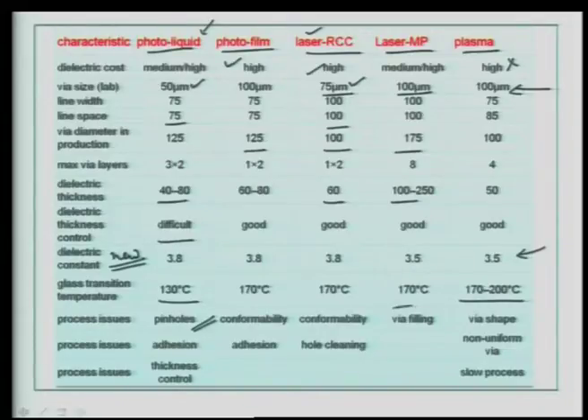In some cases, you may want to use a via filling, as I said, because you want to mount an SMD component on top of the via. Therefore, what type of filling you will do for the microvia filling, and the shape of the via in the case of a plasma seems to be well in tune with the desired results, whereas in the case of laser we could end up with a plateau like this, whereas in a plasma you might get an almost cylindrical shape. So, how do these vias behave during thermal cycling and during the life of the product are some of the key issues that designers as well as manufacturers will be interested in.